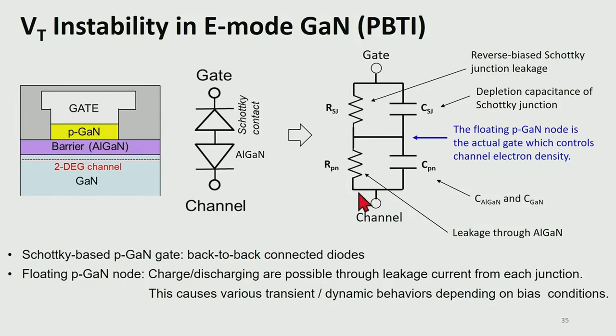In the case of the bottom junction, the resistance is mainly determined by the forward bias current, and the capacitance is a series combination of the AlGaN barrier capacitance and the gallium nitride depletion capacitance. And most importantly, this center node, which is the P-GaN, is kind of floating. And this can cause various dynamic effects.